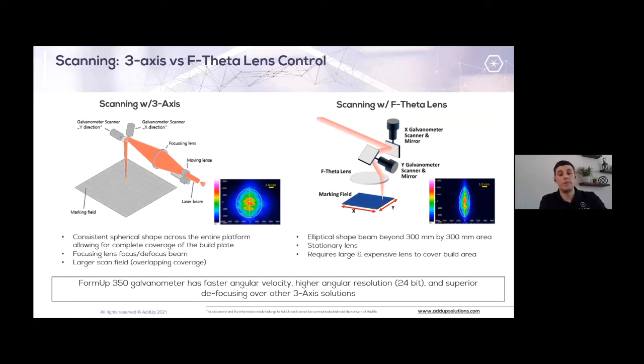So I mentioned before, we have a 3-axis scanner, and this differs from an F-theta lens control that you might see on other equipment. What this allows us to do is focus the beam in front of our galvanometers, and that allows us to maintain this spot size anywhere on the build plate. So you see on the left here, we still maintain a relatively round shape of our beam. As you get out into the edges with an F-theta lens, you get this elliptical shape that you can see here on the right.